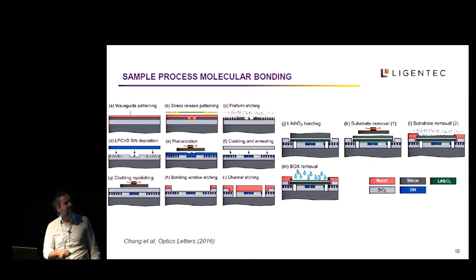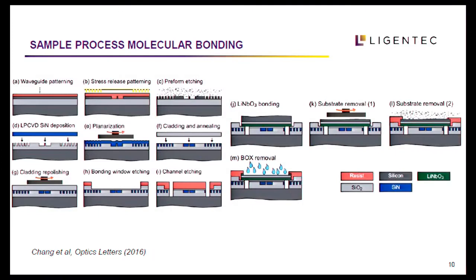And you start thinning it down in step 1, in step 2, and then when you thin it down sufficiently, you still have the buried oxide layer or some sacrificial layer of that material, which you need to remove again here. And the moment you reach this point, you say, okay, I'm done. But then you didn't do any processing on the III-V material, or in this case, the lithium niobate material. You didn't put the electrodes to connect it, so it's not electrically active. And you didn't passivate it to protect it. So this processing comes after this step. So these operations, where everything can go wrong, is just what you will call bonding. And it doesn't show the reconstitution of the wafer.